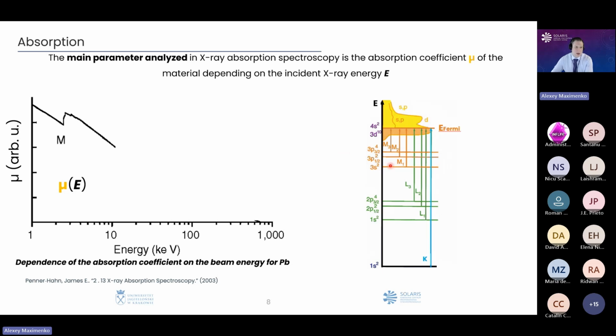But at some point, when the energy of the photons of the radiation is enough to excite the electron from the M core level, we will see a drastic increase of the absorption coefficient. And then the absorption coefficient starts to decrease again, till the moment when the energy of the photons will be enough to excite the electron from the L core level. And the same situation will appear when the energy of the photons will be enough to excite the electron from the K core level to the unoccupied states, or for example to the continuum.